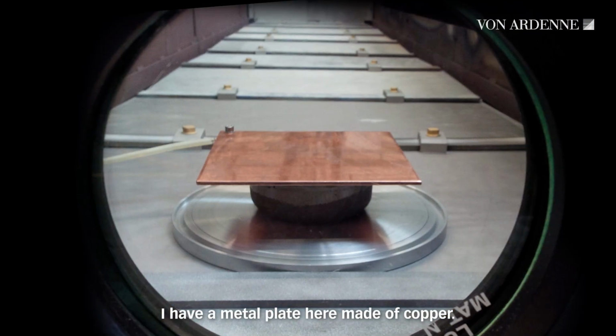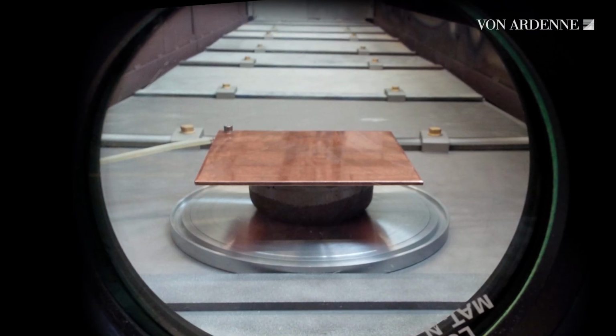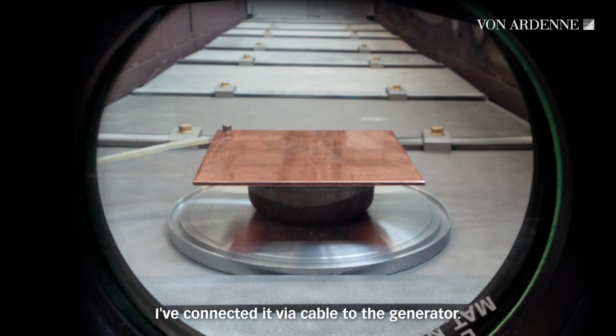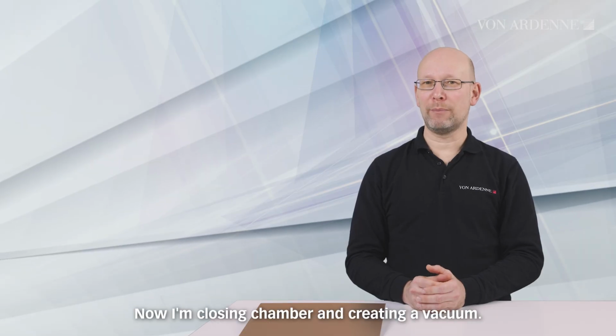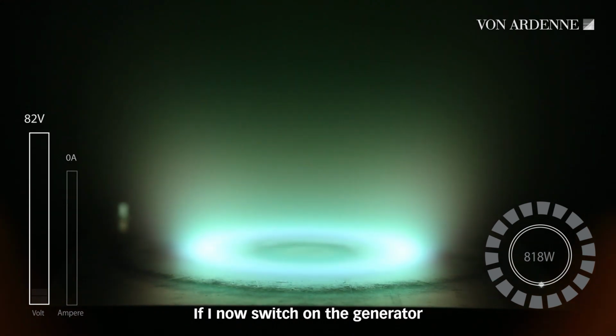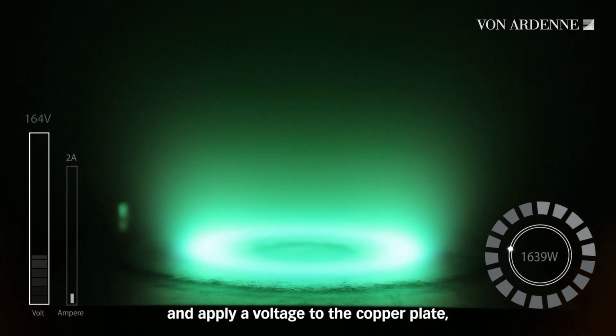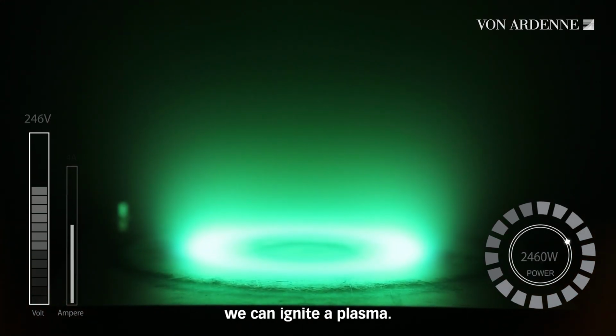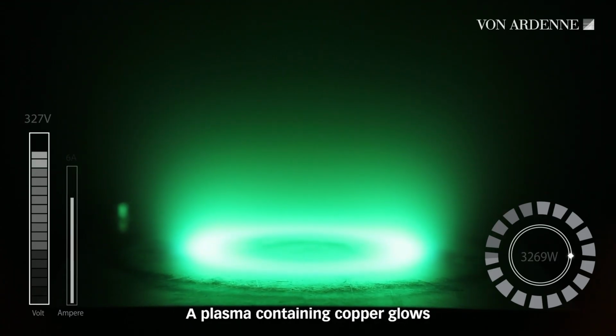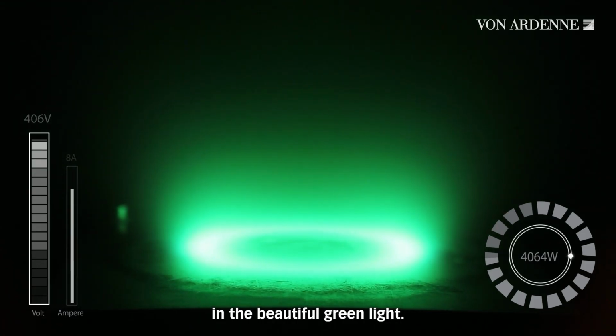I have a metal plate here made of copper. I've connected it via cable to the generator. Now I'm closing the chamber and creating a vacuum. If I now switch on the generator and apply a voltage to the copper plate, we can ignite a plasma. A plasma containing copper glows in a beautiful green light.